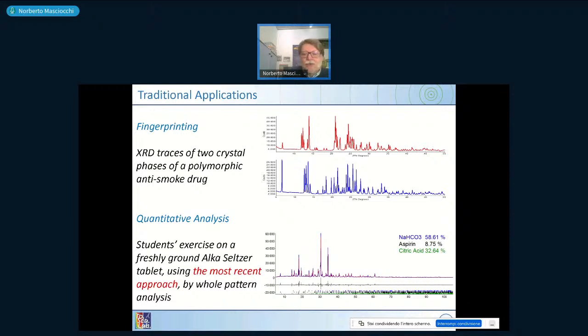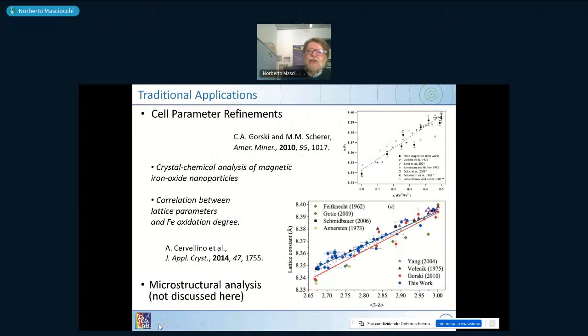Aspirin is there because it allows you to keep away your headache. And the antacid is nothing else than hydrogen carbonate, which is reacting with the hydrogen protons in your stomach. So you can say that if you measure this material in an hour, then within 10 minutes you can get information about the content and see whether the production lot of your material is confirmed, or whether you have to change it because the production, in this case by Bayer, has been wrong. Traditional application.